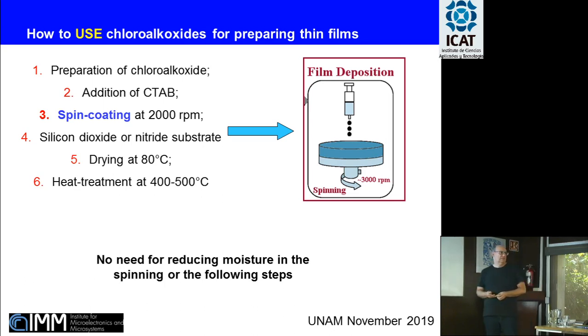With the alkoxide, what you typically have to do is to have your spin coater inside a bag. You flow some nitrogen or argon inside the bag in order to reduce the humidity, and then you can do the spin coating, but using gloves, which is quite uncomfortable. When using this precursor, they are so stable that you carry out the spin coating in the atmosphere without using any other air control.